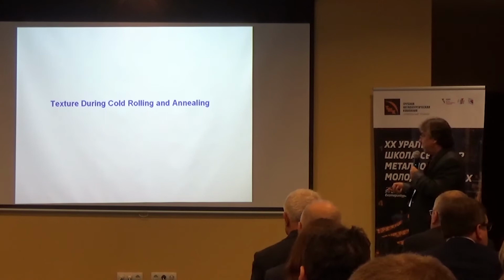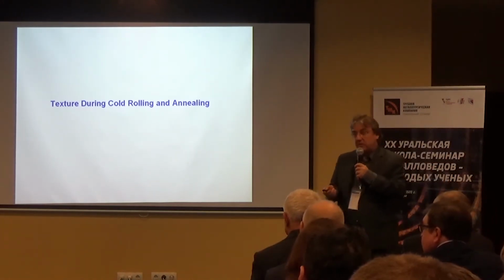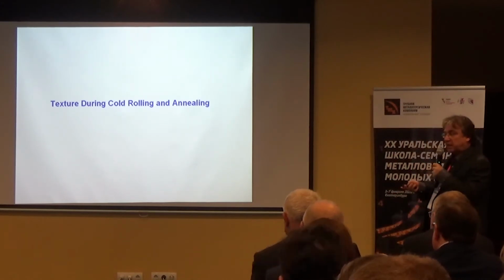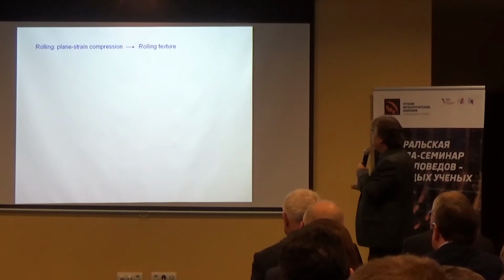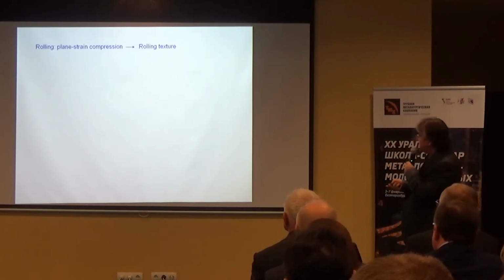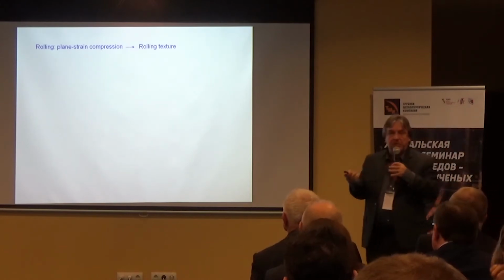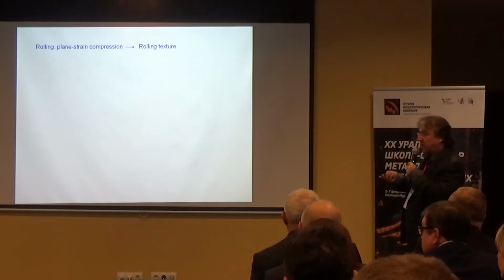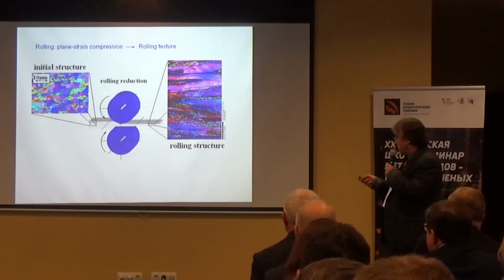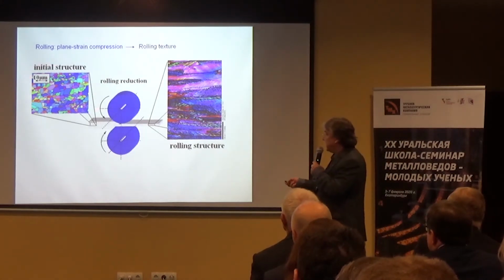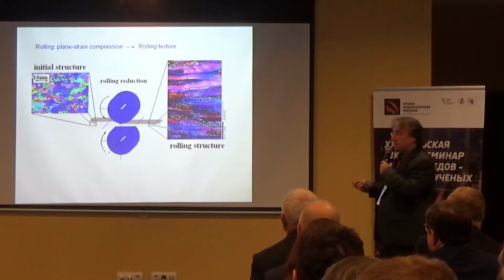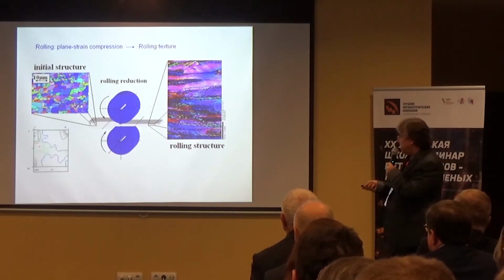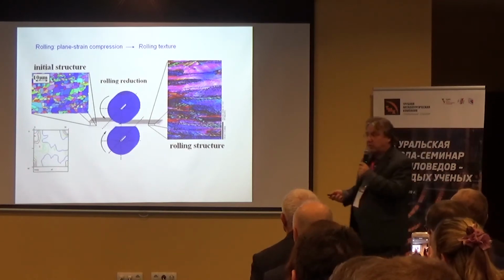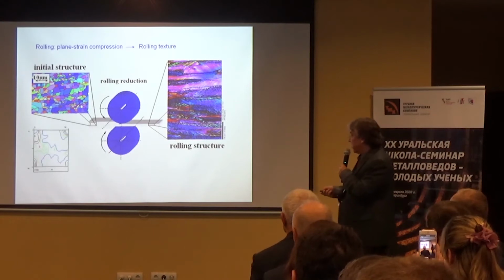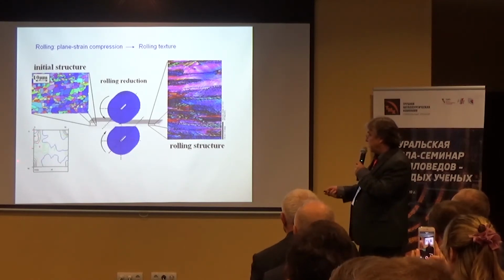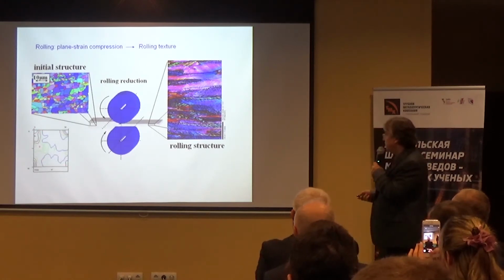Okay, sorry. So let's now have a look at an example. Perhaps one of the most traditional examples is texture formation during cold rolling and annealing. So let's assume for a moment that rolling is a simple plane strain compression deformation, and then after rolling we have a rolling texture. Here you see these are EBSD measurements. This is an initial hot band structure, in fact, and this is after cold rolling. And you can see that the hot band structure, in fact, this is a phi2 45-degree section. I will explain it a little bit more. So actually it's a very weak texture, and it has maximum on these three components.